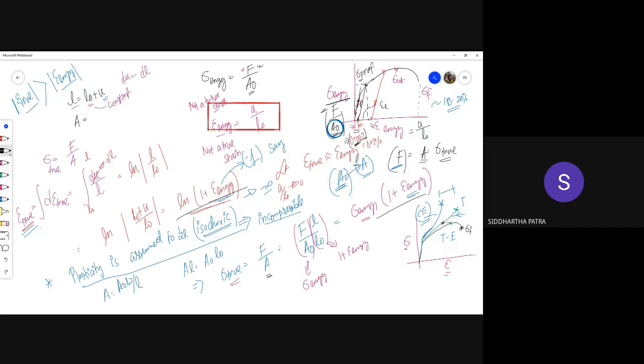Okay, so it in no way represents the limit on the elastic strain. Typically, the elastic limit would be well within 0.001. Here we are talking about 0.002, but that is the plastic strain. By the time you reach sigma proof, the total strain would be even higher than that, because there would be elastic strain of the same order of magnitude. You can say that the total strain by this point would be around 0.003 or something. Okay, so that's what proof stress is.